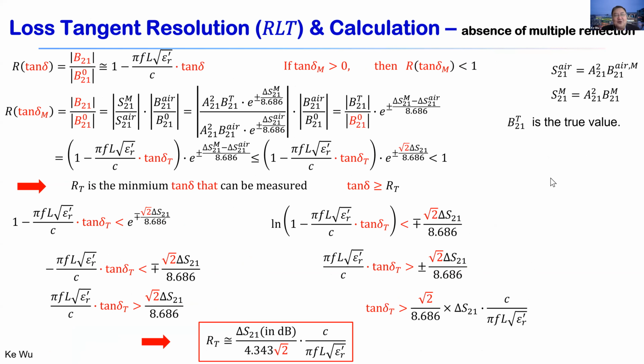And then from there, we are able to develop these ratios, and these ratios gave these formulas, and these formulas finally gave us this so-called loss tangent, which should be larger than these terms. These terms are associated with the so-called variation of the S parameters. Okay, here I will show you some of these interesting results.